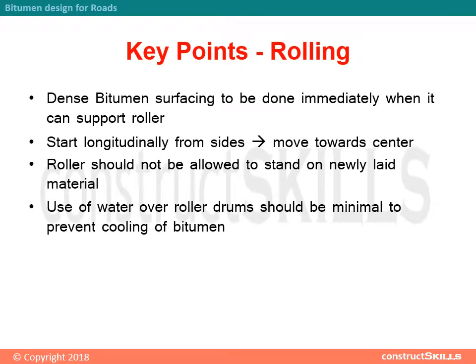Important points to remember before rolling: 1) dense bitumen surfacing to be done immediately when it can support the roller; 2) start longitudinally from the sides and move towards the center; 3) the roller should not be allowed to stand on newly laid material; 4) use of water over roller drums should be minimal to prevent cooling of bitumen.